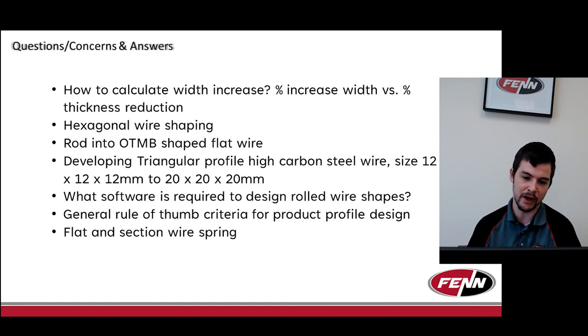When talking round wire, depending on the tensile properties in your wire, we can get various different results, but a usual good rule of thumb is you can usually cut that wire diameter in half in terms of your thickness in a single pass. For some wires that are much softer, especially copper, I've done over 60%.